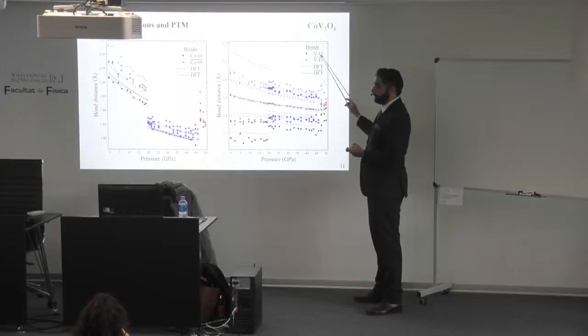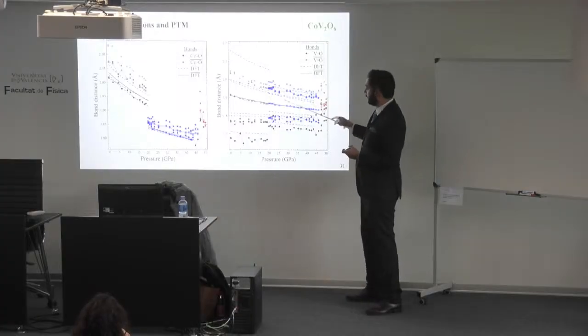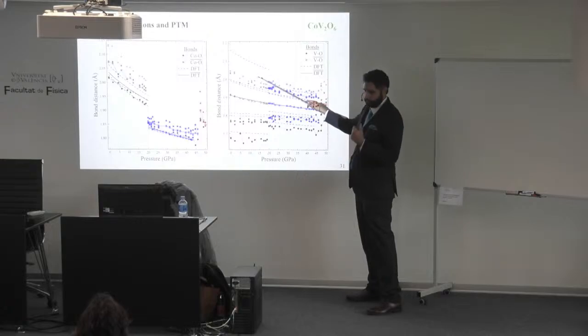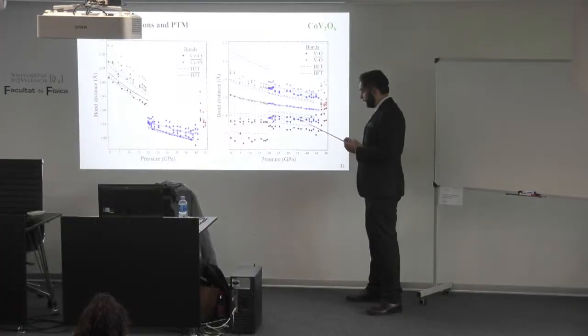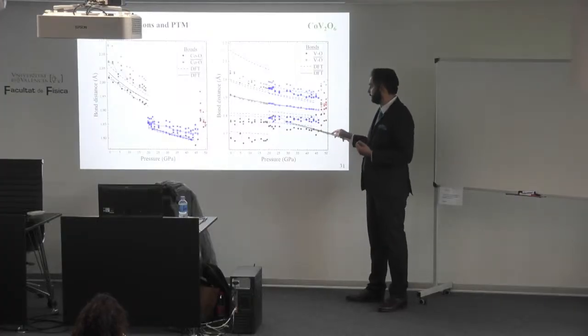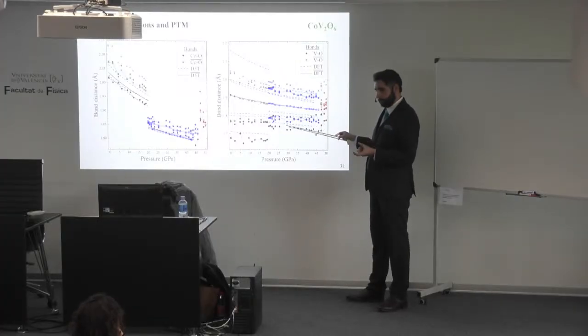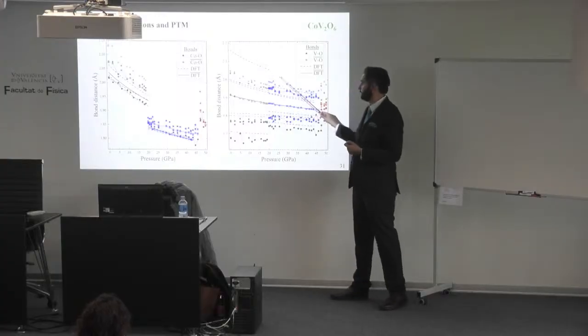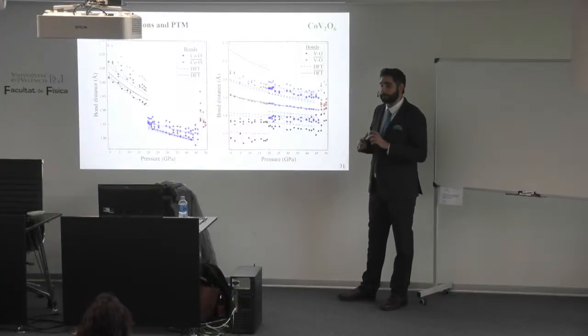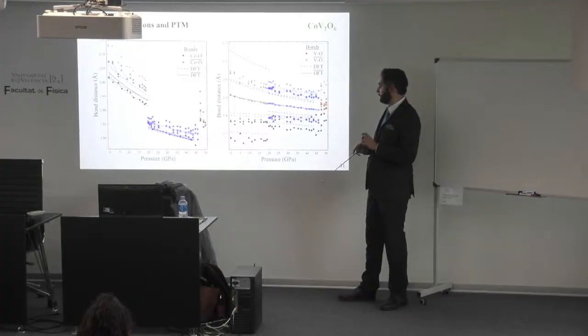In the case of the vanadium, we have 6 different bonds, 3 larger than the average and 3 shorter. In this case, the average stays the same, but the shorter one got larger and the largest got shorter. So it symmetrizes. The octahedra is more symmetrical for the vanadium case.